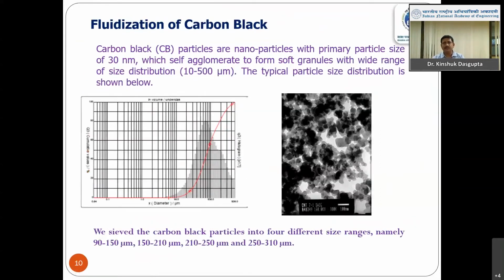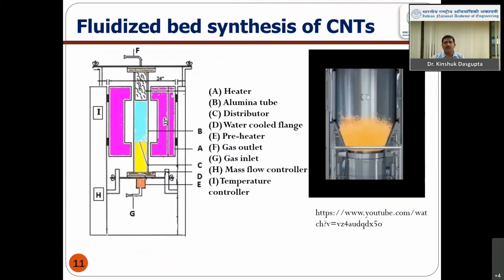And I wanted to tell about the carbon black. The beauty of carbon black is that their primary particle size is in the nano range, around 30 nanometer. But it is very difficult to fluidize nanoparticles. But this carbon black self-agglomerates and forms soft agglomerates in the size range of say 10 to 500 micron, which are easily fluidizable. And we can sieve them, get the proper size range, fluidize them and grow the carbon nanotube on that.